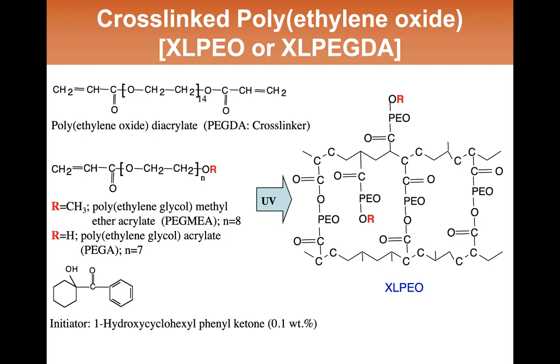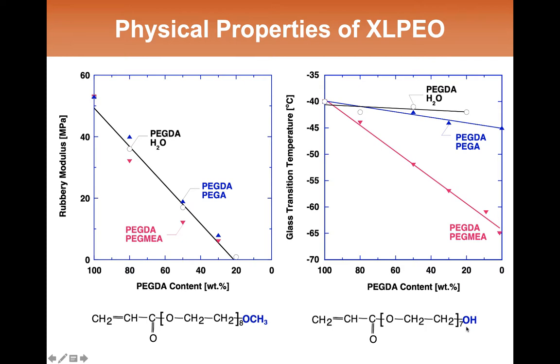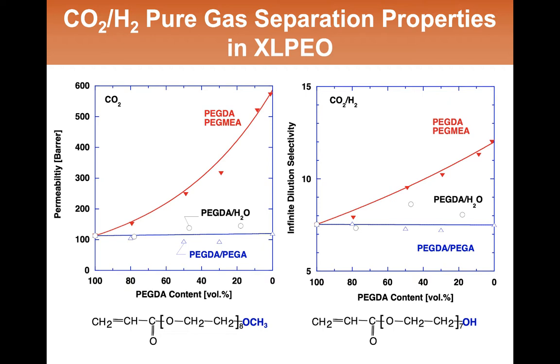That motion creates free volume, which has an impact on the transport properties, but that molecular motion also drives the glass transition temperature down. On the other hand, with this polar end group, this group is very likely interacting via hydrogen bonding with a lot of other polar groups that are in this polymer matrix, and as a result, this side group is much less mobile than this one. The decrease in glass transition temperature is much less for the PEG acrylate than the PEG methyl ether acrylate. Now, with this change in glass transition temperature, you can imagine what that would do to the transport properties.